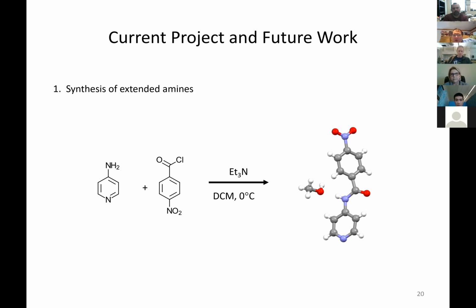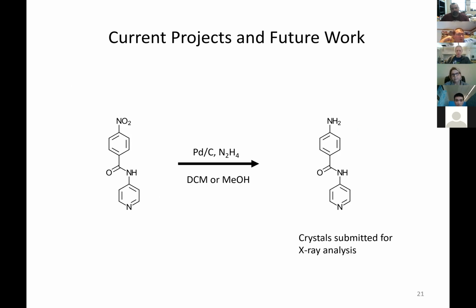So NO2 groups, nitro groups, are very easily, in literature and paper, reduced down to an NH2. So that's why we chose a method that I have used in the past, reduction with palladium on carbon and this wonderful compound called hydrazine, a component of rocket fuel. It's really bad stuff is what I want to say. But again, you can either use dichloromethane or methanol as your solvents. And again, the only change is we are converting these oxygen atoms to hydrogens. So it's a little reduction reaction.